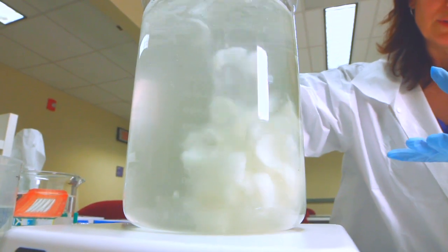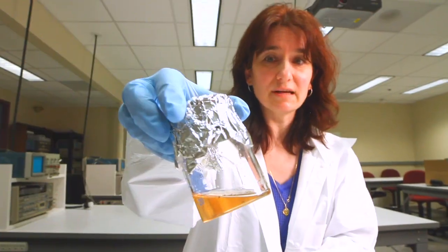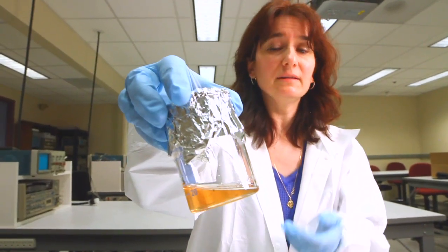After that, we're left with the pure core fibroin fibers, and those have to be essentially reverse engineered back into aqueous solution. So for that we use a high concentration of lithium salts in our lab.